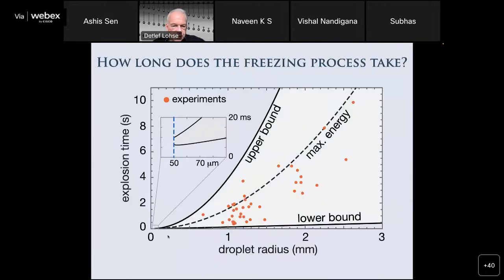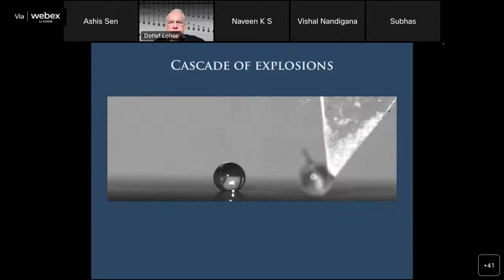And in fact, this was in this drawing here, which I didn't show you before, but if you zoom in, you see that below 50 micrometers, this process cannot happen. So only for these larger droplets. And this apparently plays a very important role in the formation of hail and ice out of the supercooled clouds. But why is it happening all of a sudden? Well, there's a cascade process.